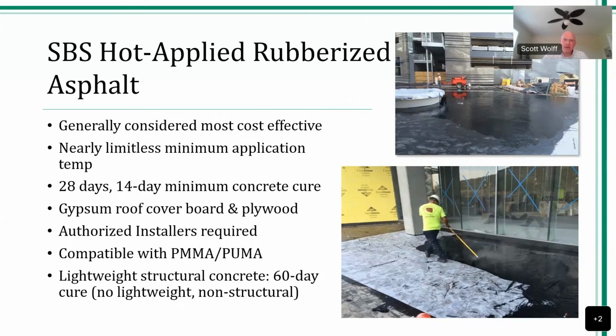But the caveats to hot applied rubberized asphalt is ideally 28-day cure time. Manufacturers generally accept 14 days minimum. This is just how it is. Concrete has a lot of moisture in it. If our concrete is lightweight structural concrete, and I emphasize structural, the minimum cure time is 60 days. Lightweight structural concrete is hydrated for several days before it's poured and uses a slightly different aggregate. So hence the reason the bound moisture takes that much longer to basically be released.